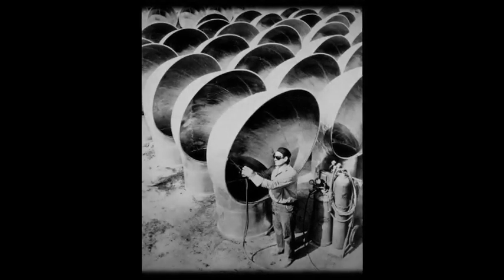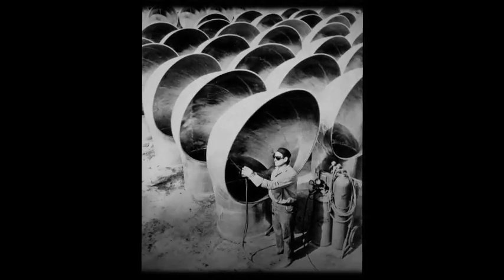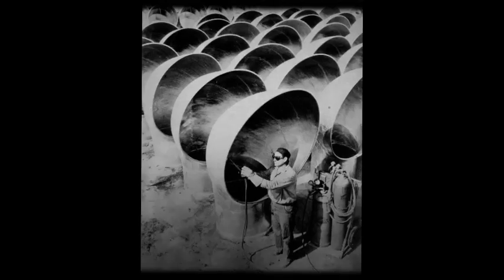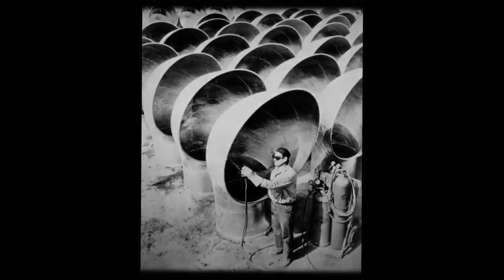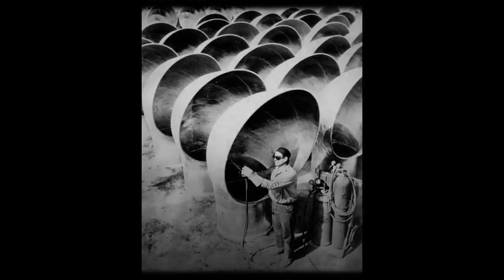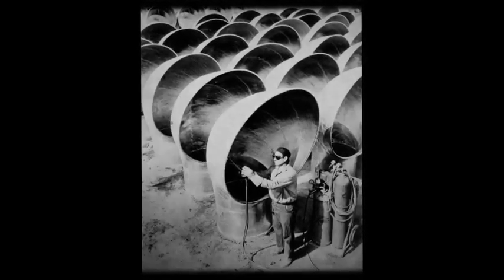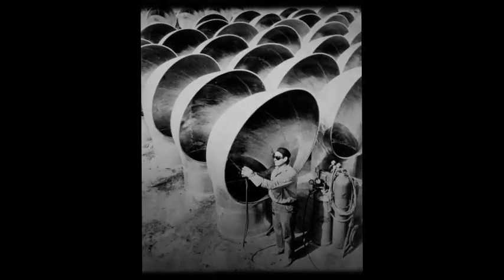The stress at one hatch corner started a crack. That crack found a straight path through the long welded deck plates. There were no rivets to slow it, no breaks to arrest the crack. The crack tore through the ship in seconds, letting out huge stored energy all at once in a total failure.